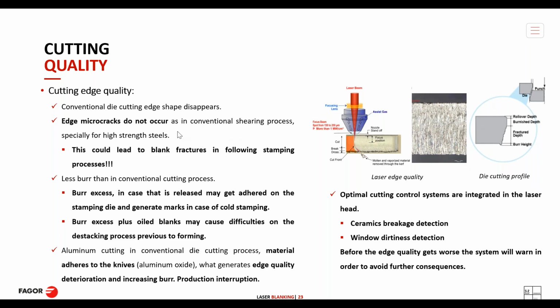So by mechanical cutting with a conventional die, the shearing process, especially with high strength steels, may provoke some edge micro cracks that could lead afterwards to blank fractures in following stamping process. Well, I'm talking in this case about cold stamping. Additionally, as I said, less burr than in a conventional cutting process is generated, and this burr could also be a problem, because if in the forming process this burr is released, it might get adhered to the stamping die and generate some marks, right?